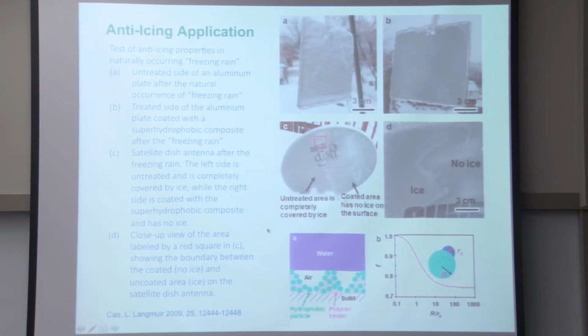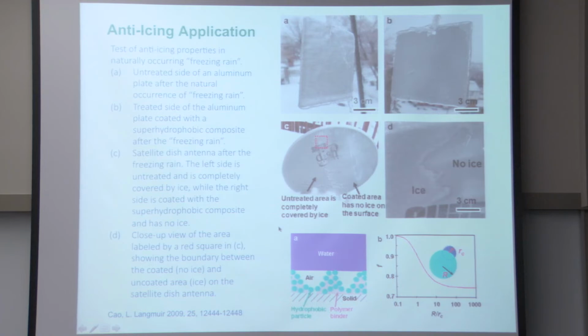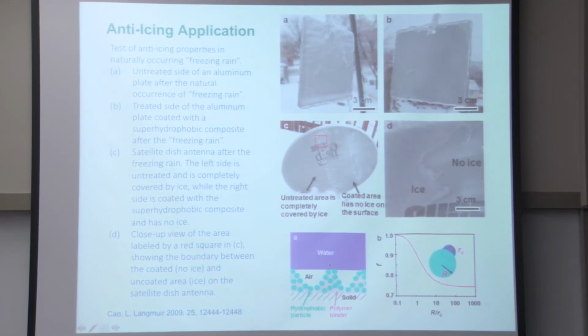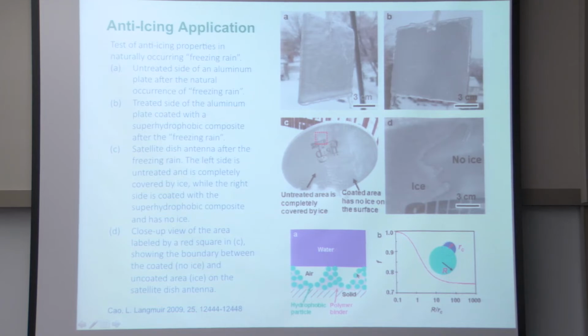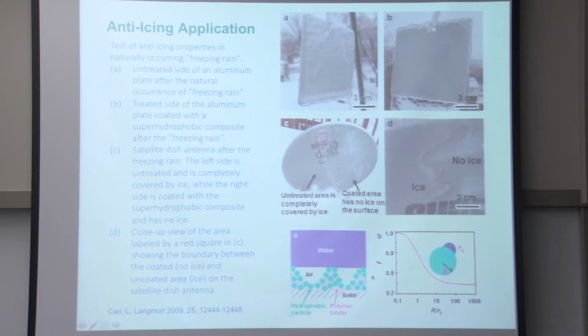Many surfaces with a superhydrophobic coating result in trapped air between the solid rough surface, employing the Cassie-Baxter approach, preventing ice crystals from forming in the first place. These are static tests. There are other tests based on wind tunnels and shear forces, and other applications that merit tests based on ASTM standards or FAA.